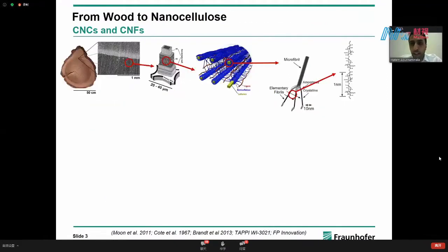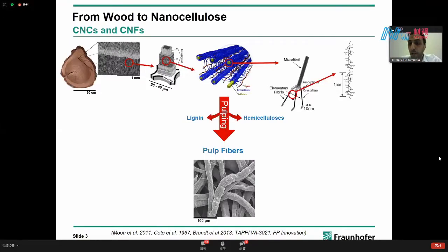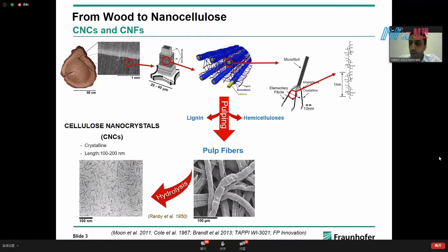Now, I don't really want to go into detail about wood structure and all these anatomical features, but we all know that wood in general is made of lignin, hemicelluloses, and cellulose. In the pulp and paper industry, usually lignin and hemicellulose are taken away through standard and traditional pulping processes to produce 20 to 40 micrometer thick cellulose fibers. Out of these thick fibers, we can make one form of nanocellulose called cellulose nanocrystals. These nanocrystals are crystalline, rod-like nanoparticles with a thickness of a few nanometers and a length between 100 to 200 nanometers. For sure, there are even longer nanocrystals than these, but let's say this is pretty much the standard. These cellulose nanocrystals are produced by treating pulp fibers with a strong acid such as sulfuric acid in a chemical hydrolysis synthesis route.